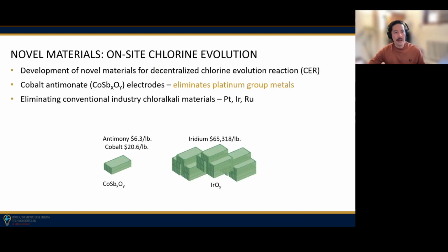So how does this fit into what we're doing in our lab? One example that I'll show you today is the synthesis of chlorine. I've mentioned chlorine a few times now, but how can we make chlorine on site at a water treatment, say a remote water treatment system, instead of having to truck in or train in hypochlorite or chlorine? It's worth mentioning that currently about 90% of all chlorine, whether it's for water treatment or pulp and paper processes, is made electrochemically. The problem is that the gold standard electrode involves platinum group metals, so metals like platinum, iridium, and ruthenium, which make it a very expensive process, both from a capital expenditure as well as an operational expenditure, because these electrodes don't last forever.